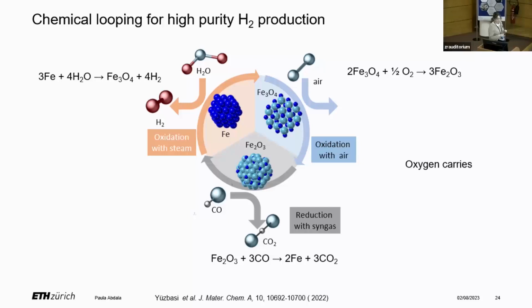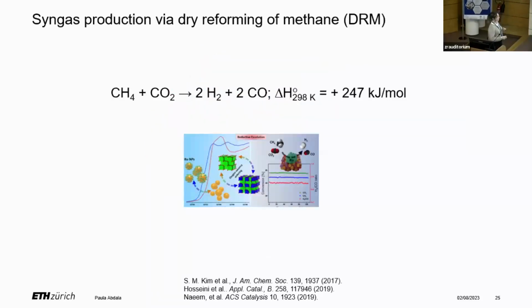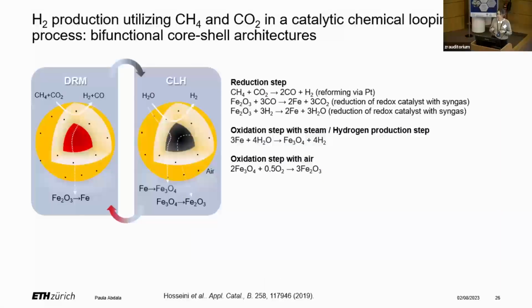To reduce the iron oxide, we need syngas. So we can, in principle, use the dry reforming of methane. So methane plus CO2 will give syngas, and we can use it in a different process. But what we thought is, what if we integrate these two processes at the particle level?